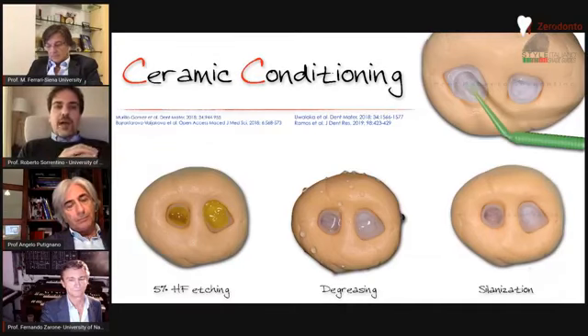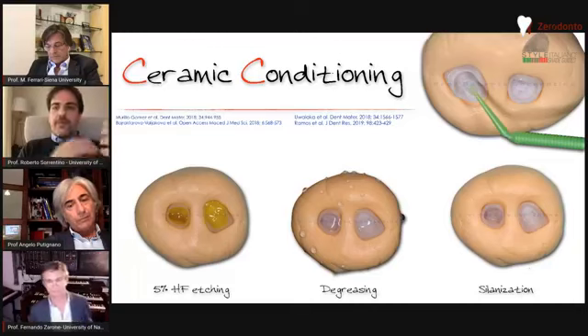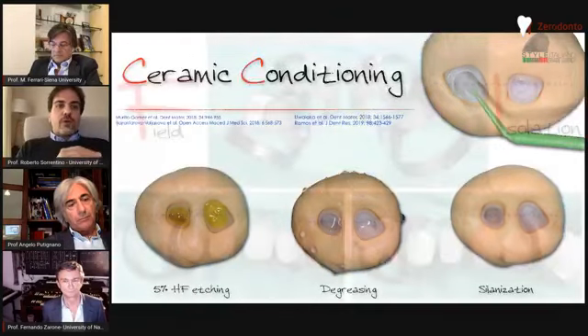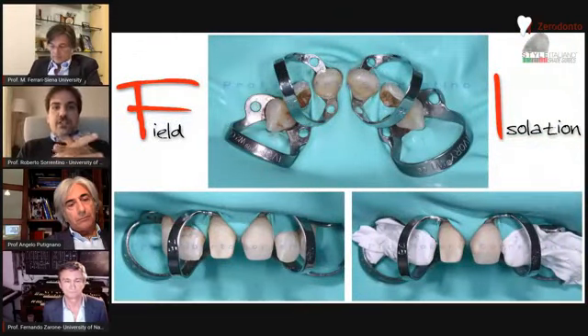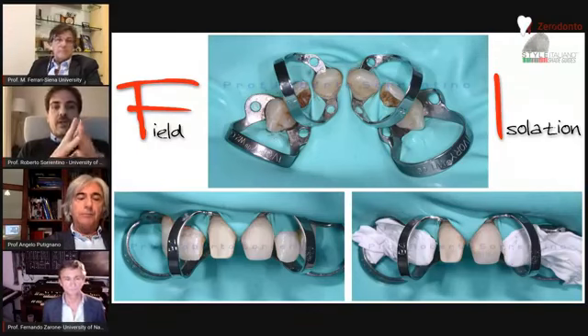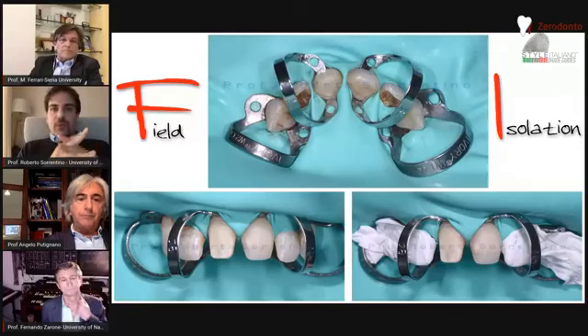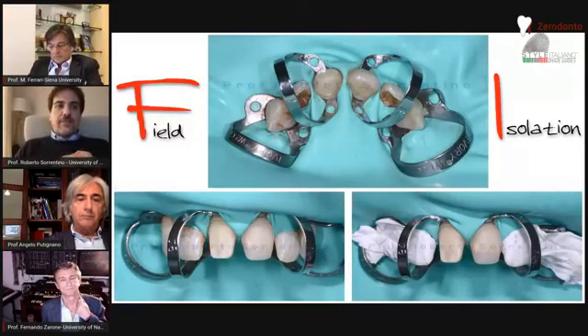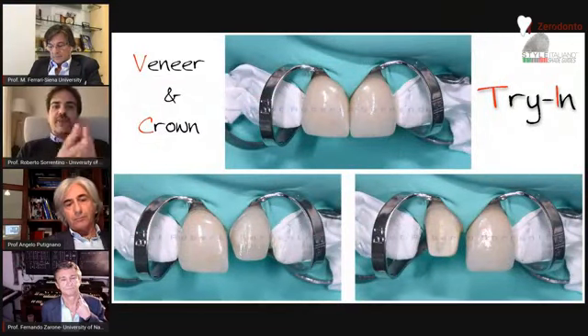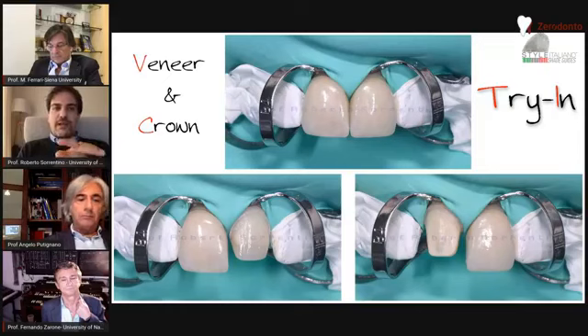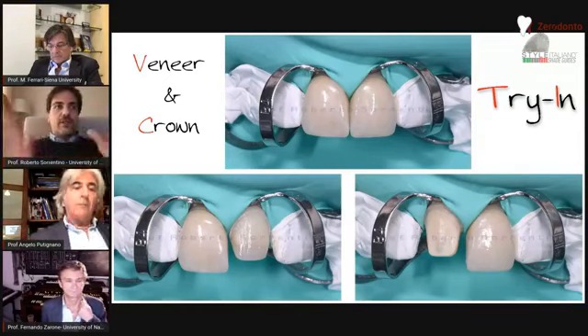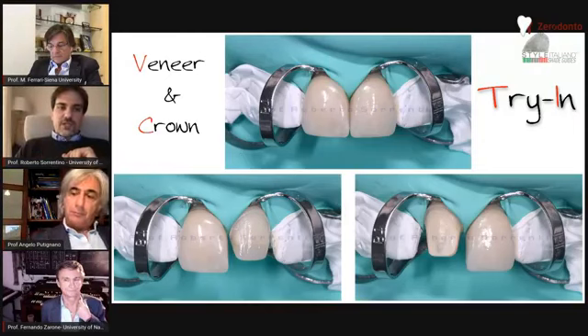And finally, the application of coupling agents, like MDP-containing primers or silanes, according to the resin cement you are going to use. It is well known, as you have anticipated, that the achievement of good adhesion relies on the management of clean surfaces. In this perspective, isolation by means of the rubber dam is mandatory to prevent any contact with blood, saliva, and other contaminating agents. And the careful control of moisture is an indispensable prerequisite to obtain the best bond strength, which can be reduced by up to half in the presence of contaminants. And here you can see the try-in of the restorations.